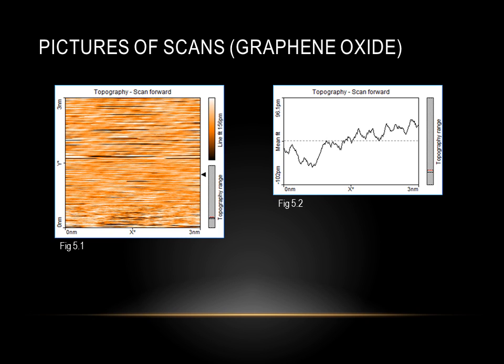Finally, the most interesting part of the project. We have the image and topography of graphene oxide, a single layer of graphite sheet with oxygen atoms on it. It shows that compared to gold, images of graphene oxide are possible to be obtained, but the resolution is less than that of HOPG. The wavy nature of the image reflects the elastic nature and the creases on the graphite sheet. The atomic distances match those predicted in theory.